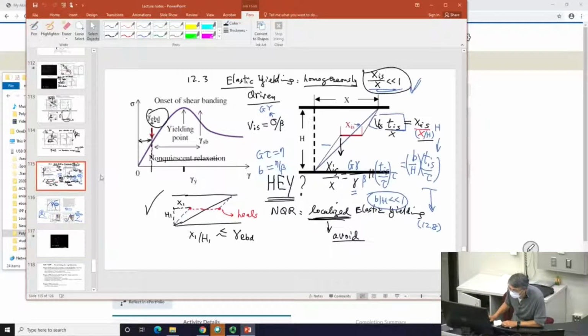In other words, I want to indicate, maybe through this figure, that if you don't stop your shear, you start to see the sample break up well after the overshoot. Yet, if you stop shearing, the breakup could occur way before the overshoot. That's perplexing.